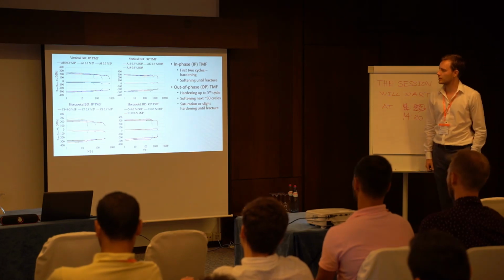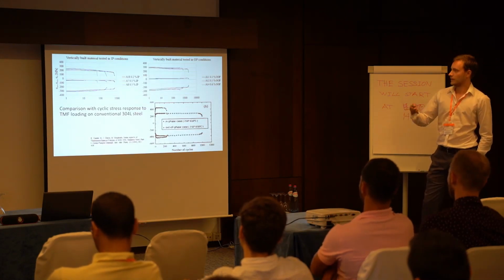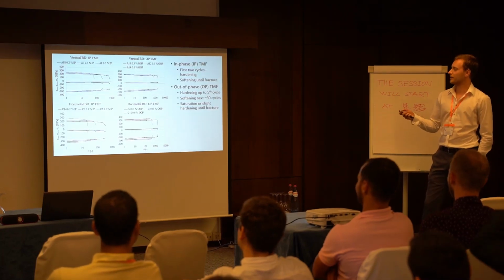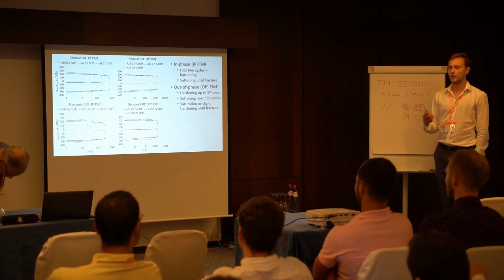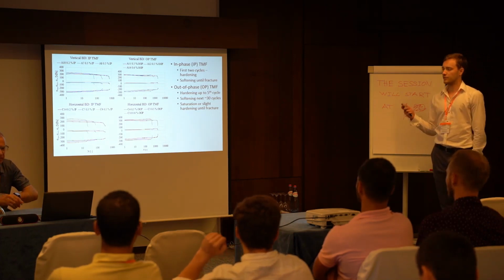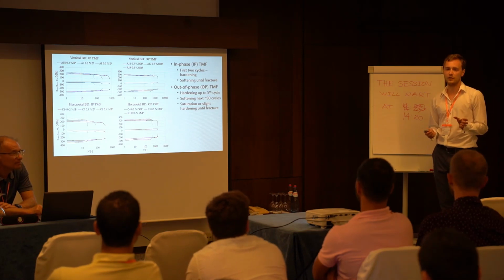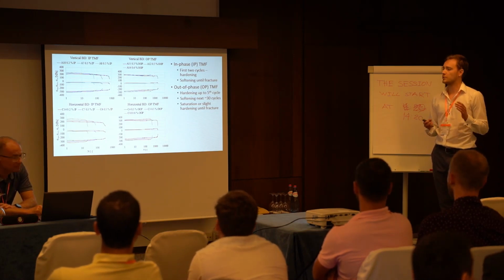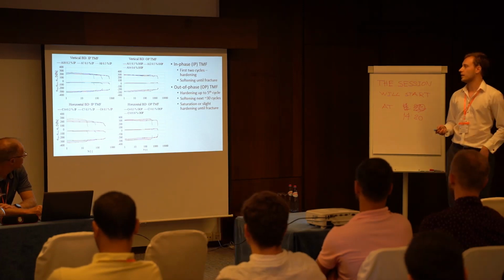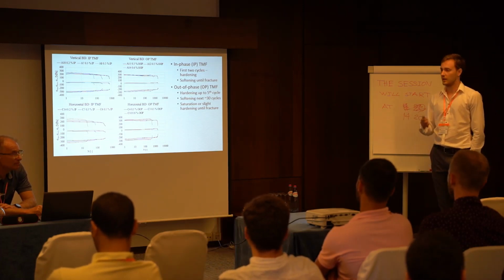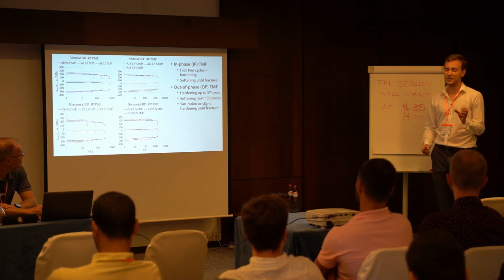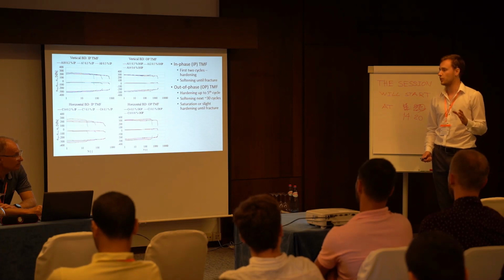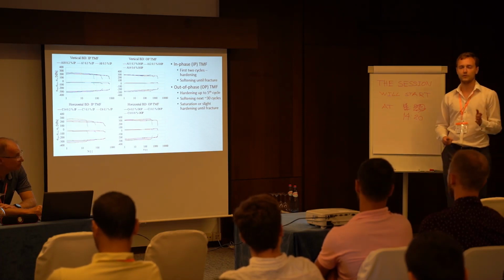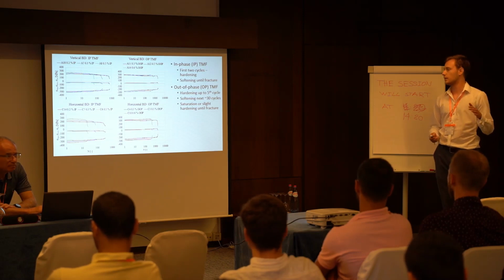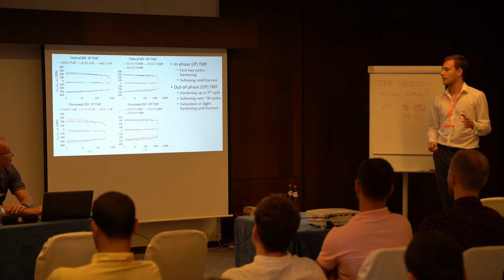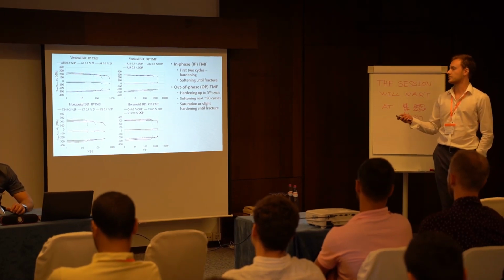Okay, so now let's take a look at some charts. Here we have cyclic hardening and cyclic softening curves. So generally, just to take it briefly, in case of in-phase tests, we saw cyclic hardening for the first 2 cycles at maximum, which was followed by gradual softening until fracture. In case of out-of-phase tests, in both building directions, we saw an initial period of cyclic hardening up to 5 cycles, which was followed by again a rather short period of softening for about 30 cycles, which was followed then by saturation of cyclic stress response. In some cases, there was even slight hardening present.